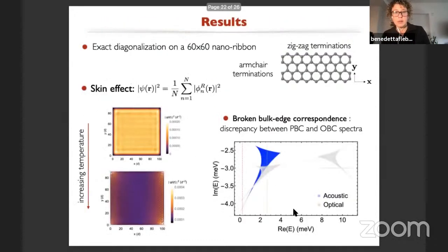So let me show you our results. We took our Hamiltonian and we diagonalized it over fully open boundary conditions. So here we have zigzag termination on one side and armchair on the other. And one way to start looking at the skin effect, which is what has been done in the literature according to its definition, is to look at the spatial distribution of the density of the right eigenstates of the system.